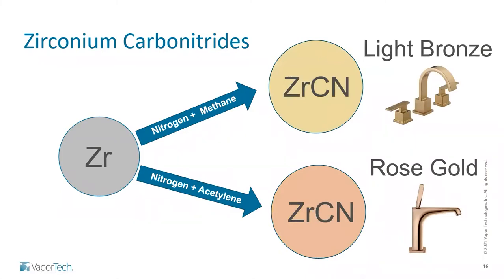And very similarly, nitrogen and carbon gases, you get carbonitrides. And there are two carbon gases we use most often, methane and acetylene. They can often be used interchangeably, but just in this quick example, sometimes you just get different shades of colors. And we tend to get a little bit more red when we start using acetylene than we do with methane. So you get some more of the rose gold colors. However, methane tends to be what we call a cleaner gas or more thermally stable.